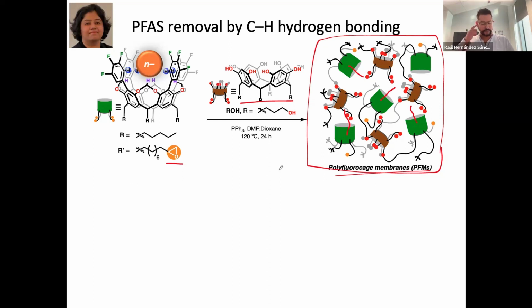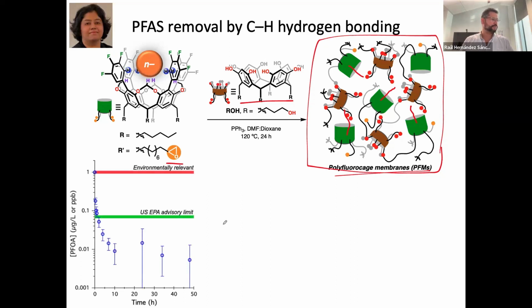That's the whole idea. And so we tested this, and this was one of the first results. You can see here, we're using PFOA starting at 1 part per billion, and the residual concentration in that water is going rapidly down in a matter of hours, and then it somewhat stabilizes past 10 hours at levels that are relevant to the problem at stake. So, for example, here at 48 hours, somewhere here, right? So this is 1, 2, 3, 4, 5. So this is 4, 5 ppt. So we're somewhat getting to the target value, right?